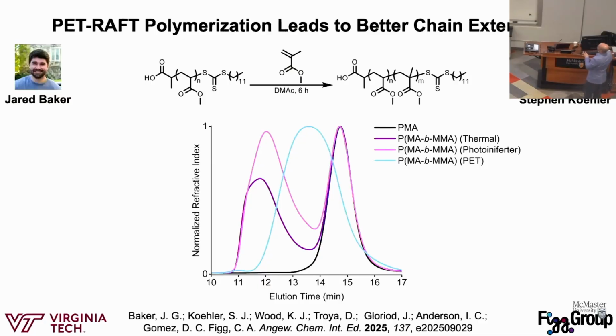So this slide is just showing some controls. Here's our PMA chain end, and we want to chain extend it with methyl methacrylate. This black size exclusion chromatogram is our starting polymer. This is showing elution time on SEC, so big things elute sooner, so we want to shift to the left. If we just do a conventional thermal polymerization, which is the purple trace, you see it's very ugly, and you don't want a bimodal distribution unless you want a bimodal distribution in your GPC, right? So this is not what we want.